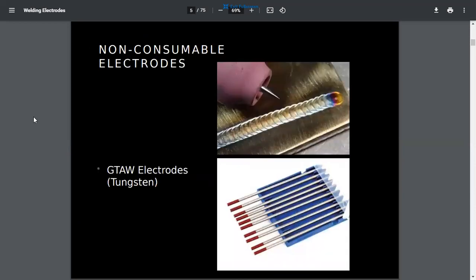And then we have non-consumable. We got tungsten for the TIG process. Those should not end up in your weld puddle, although if you are learning, there is a chance that the tip of your tungsten will end up in a weld puddle at some point. If that weld needs to be inspected, we need to get that tungsten out of there. You got to grind that out, get it gone, because we don't want those inclusions.